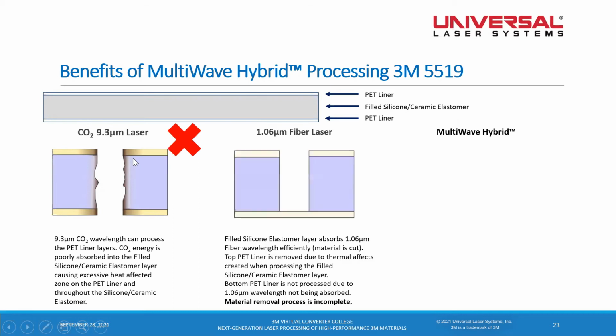So it's really not a good answer. The middle layer, this filled silicone ceramic elastomer, absorbs the 1.06 wavelength quite well, but it's actually transmissive, or it goes through the PET layer. By applying 1.06 only to the material, we're able to remove the middle layer, the filled silicone layer, and through the thermal effects, the top layer of PET was effectively burned off. But the bottom layer remained. This is a great kiss cut, but it's not an ideal through cut.